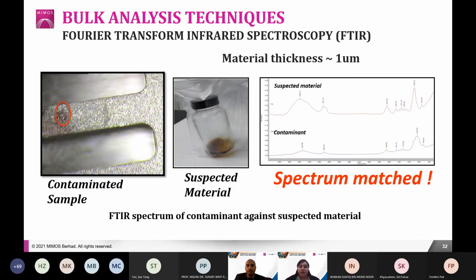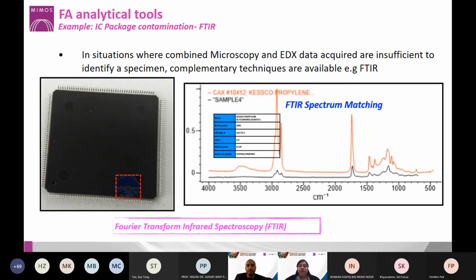So for FTIR, Fourier Transform Infrared Spectroscopy, if there is a suspected material on the contaminated sample, we would match the spectrum to identify that the suspected material is on the contaminated sample, okay? And in situations whereby the microscopy and EDX data is not sufficient, so you feel I still need to identify what this specimen is, I'm not happy with what I've got, you can use FTIR spectrum matching as a complementary technique. If we don't have the suspected material, we would get it from the library when we do the spectrum matching, and you can get the particular information.